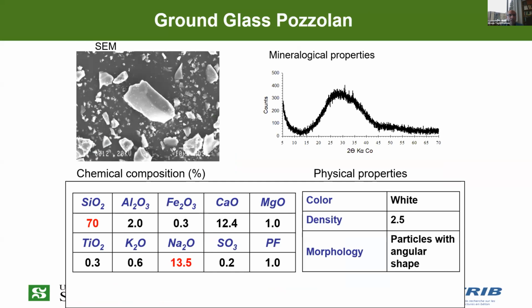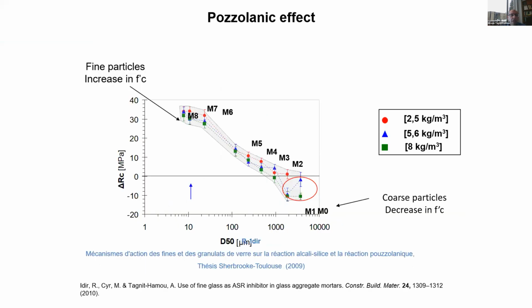So ground glass pozzolan is an amorphous material. You can see here by this XRD, it is rich in silica oxides, also around 70%. But of course, there are alkalis in one type. The other type is free of alkali, but the major amounts have high alkali content.